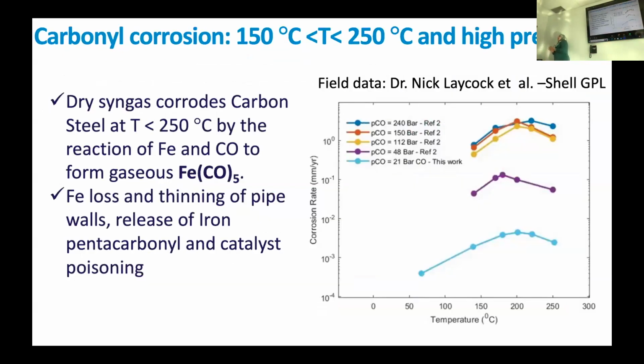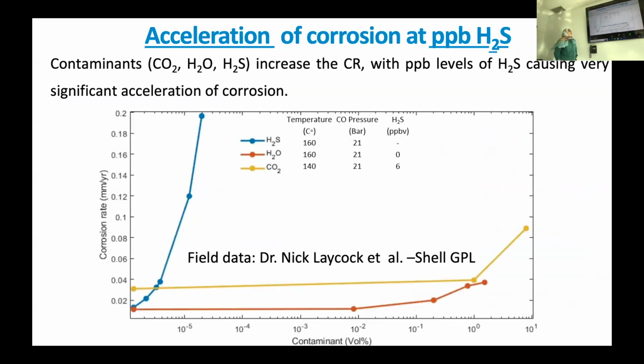Now, very quickly, the second problem, which is the opposite, right? What happens in the opposite case, which is at lower temperature but higher pressure, is that when you flow syngas, which is CO, hydrogen, some water, and so on, instead of CO sticking on the surface and decomposing, you're removing iron and creating this gas. And this is happening. So these are some experimental results. As I explained to you, we had this challenge to explain why H2S in this case is increasing the carbonyl corrosion, which couldn't be explained from intuition or by people in the field.